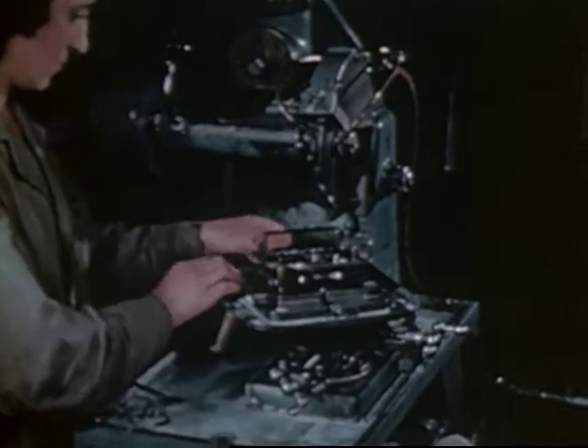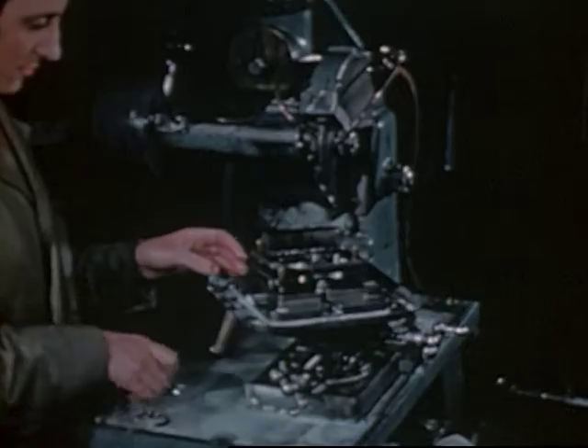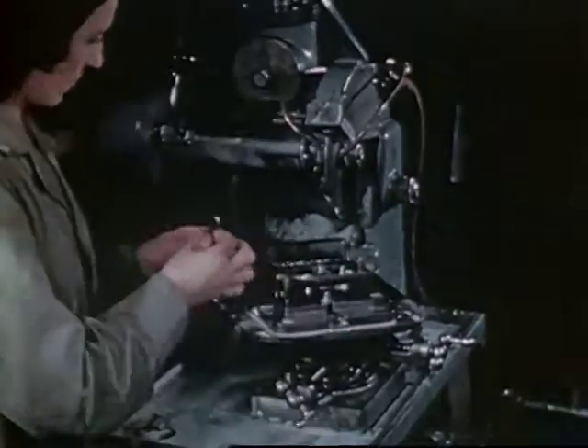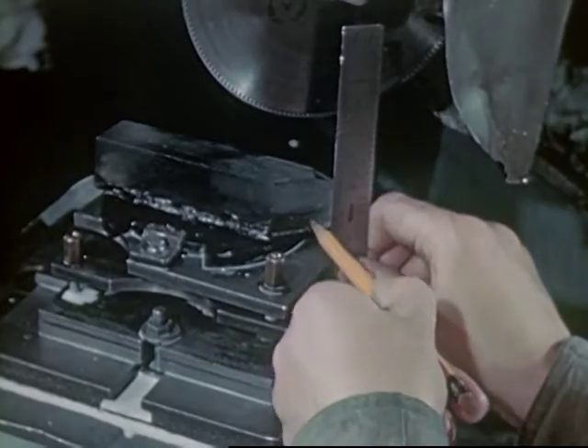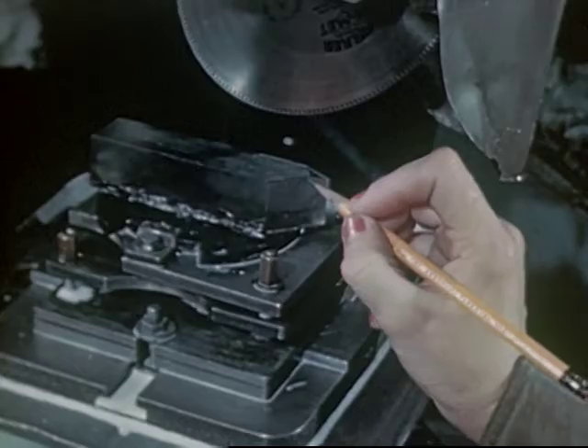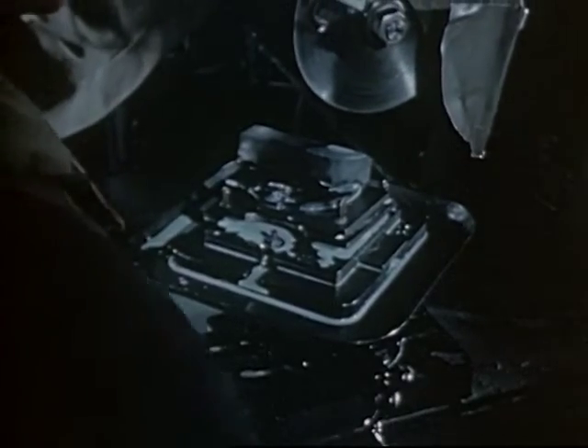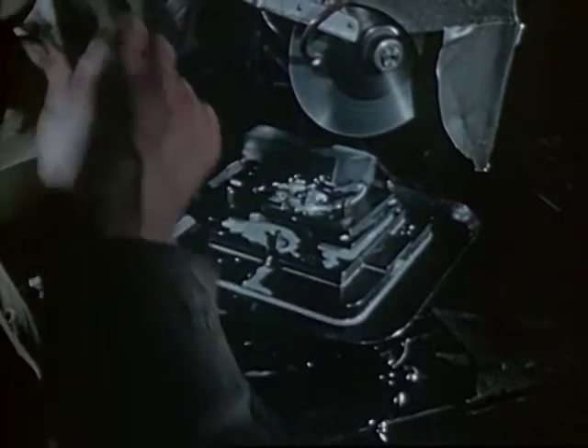Vertical arrows have been drawn on the quartz in 2 previous operations so that the crystal would not get inverted. After the jig is firmly bolted to the saw head, a preliminary cut is made to remove the end of the bar, and again an identifying arrow is drawn to keep track of the up direction of the first wafer to be cut. The rough wafers are rarely more than 1/16 of an inch thick, and it is quite an art to saw them thin and true from this hard and brittle material.